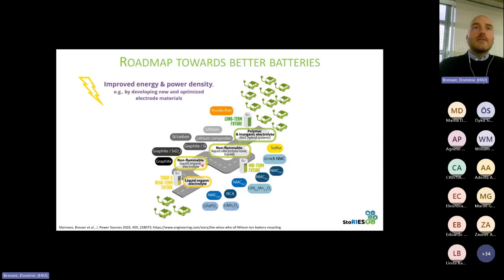And what I said on the previous slide, so when it's about improving energy and especially power density, then we need to think about other materials on the negative electrode. And the clear idea is to go from graphite to graphite-silicon oxide or graphite-silicon, which is, I think, increasingly the state of the art, to silicon-carbon composites, right, with an increasing fraction of silicon. And then ideally metallic lithium, and/or metallic lithium in so-called anode-free concepts or zero-excess concepts, which I will introduce towards the end of this talk.